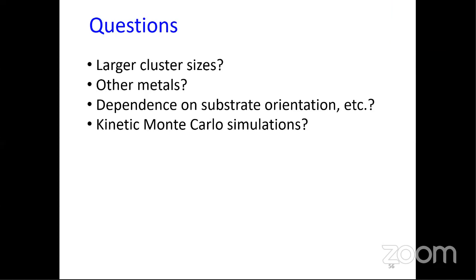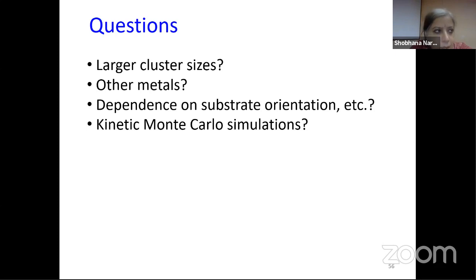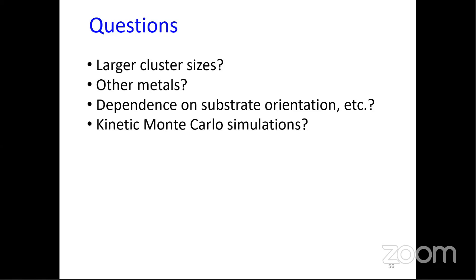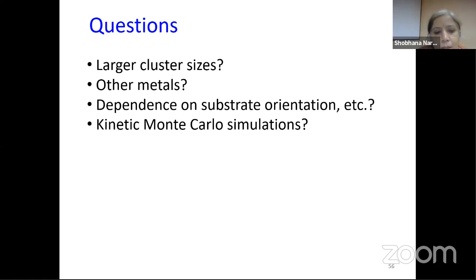Okay. The second question is with your metal dependency. What makes the platinum different from gold and silver? So was relativistic effect, especially the scalar relativistic effect, included in the calculation? So scalar relativistic effects are there, but not full relativistic effects. We do not believe that for these kinds of properties, the full relativistic effects are important. I mean like spin orbit or something, I don't think is important. I meant scalar relativistic. Yeah, scalar relativistic is of course there. And so what really seems to be important is just the strength of the interatomic interactions.